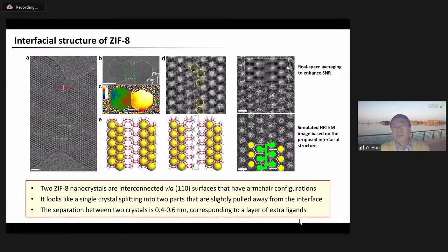So based on the HRTEM image, we could analyze the interfacial structure, and the result shows that at the crystal interface, there is an additional layer of the imidazole ligands compared to the bulk structure. Okay, so this is the bulk structure model, and this is the structure model for the interface. We see the difference. And therefore, at the interface, there are some large cavities generated. So this helps to understand how the assembly of ZIF-8 nanocrystals influences its gas transport property. Because when you have this assembly